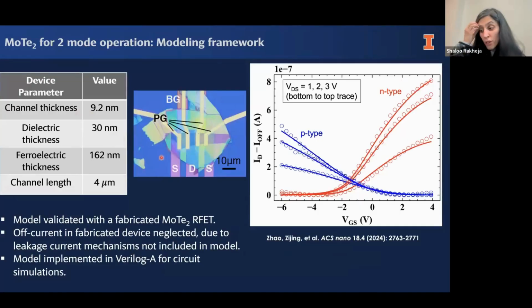And once we have our model, we can actually calibrate it with the measurements. So here are the device parameters, and our model, which is the solid line, shows a really good match with the experimental data, which is these circles over here.